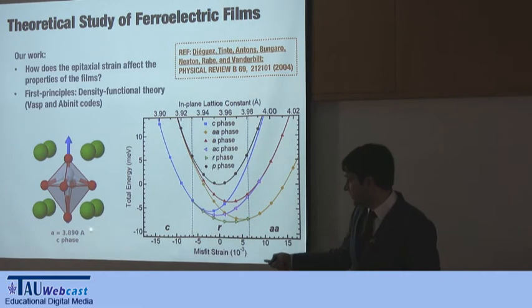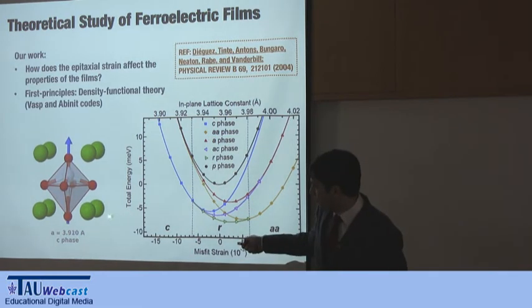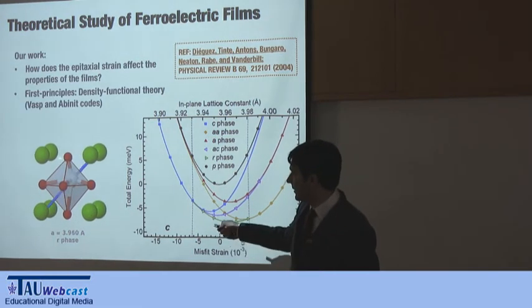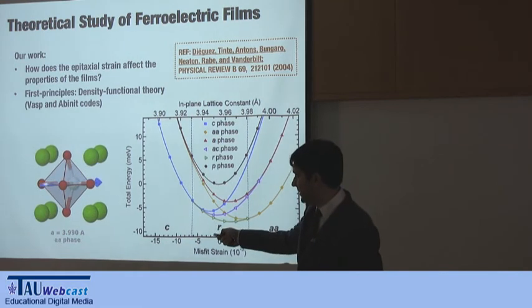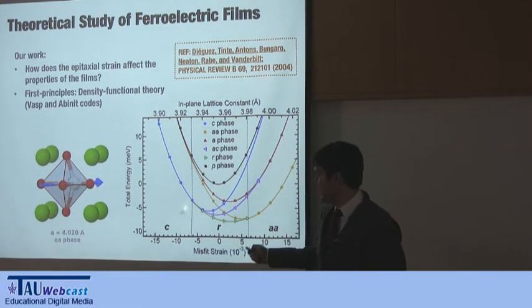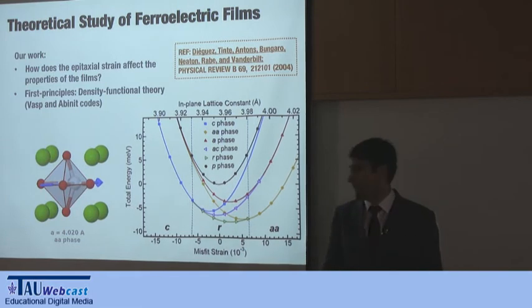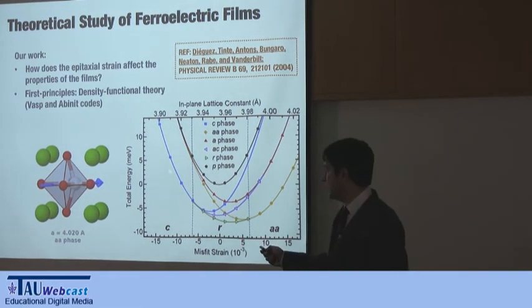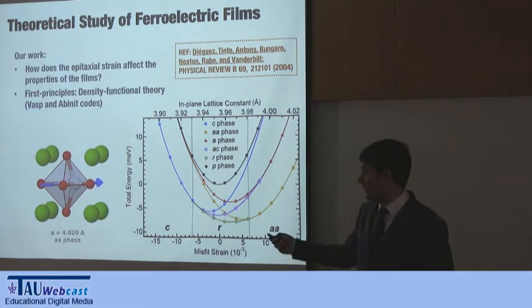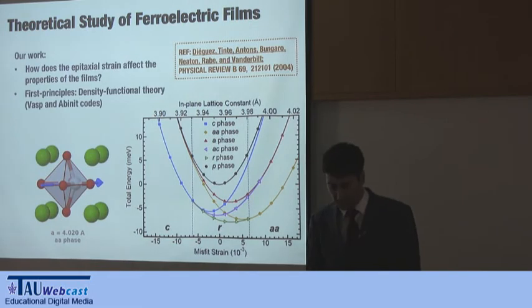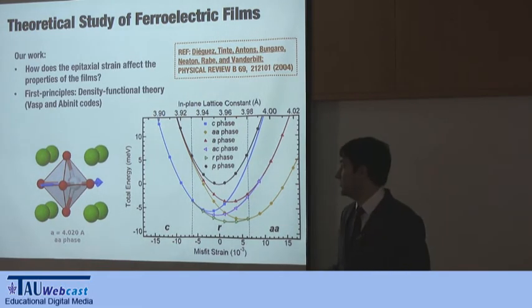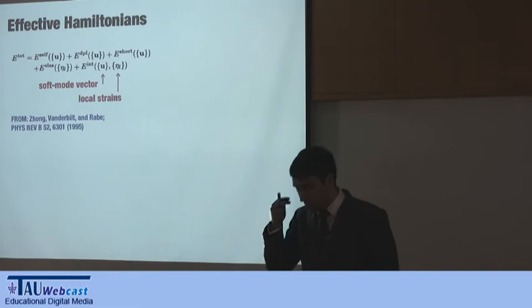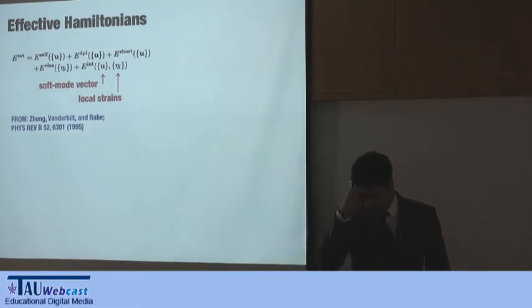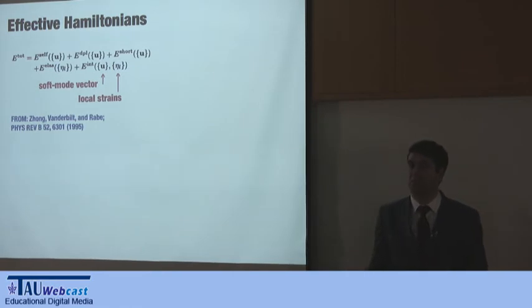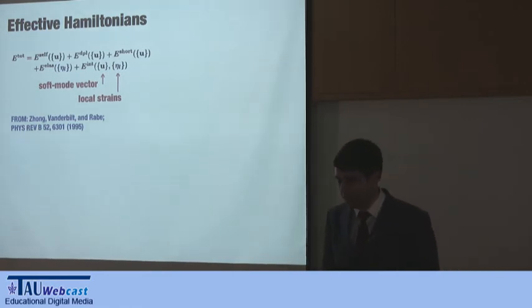So what happens is that as you squeeze the material, the polarization rotates. This is the R phase, and this is the AA phase. And this is a second order phase transition in the sense that it's a continuous movement of the polarization as a function of strain. And this had not been reported before. So this is what you get at 0 temperature. Okay? Those DFT calculations are usually, or by default, done at 0 temperature.